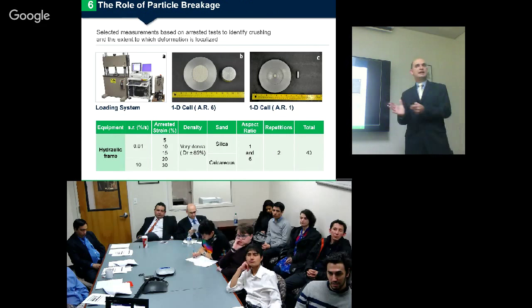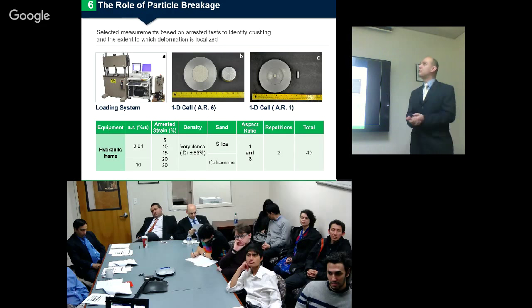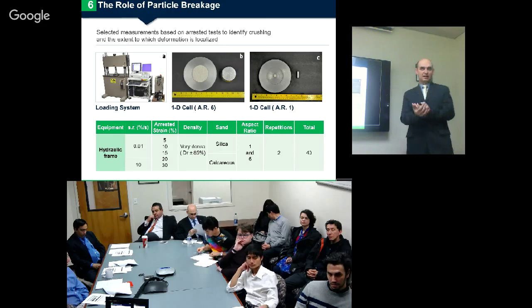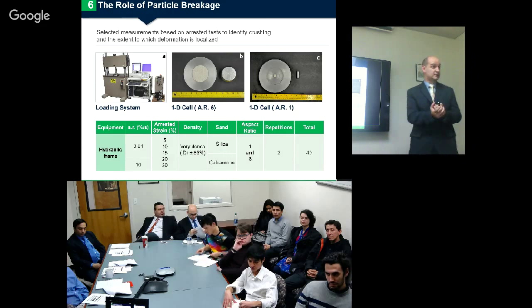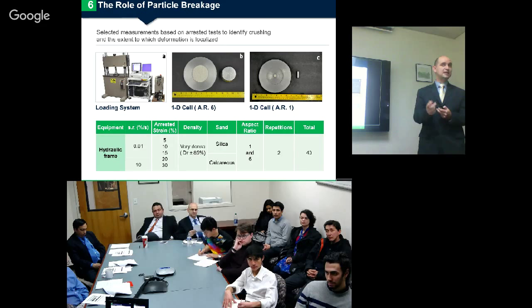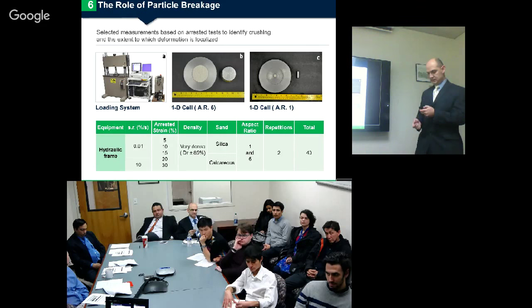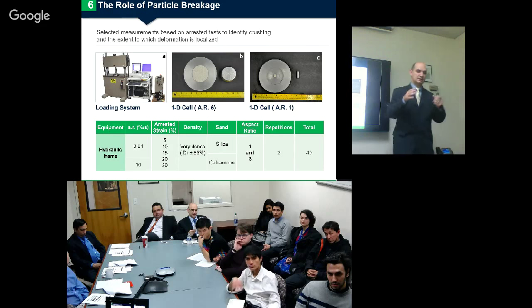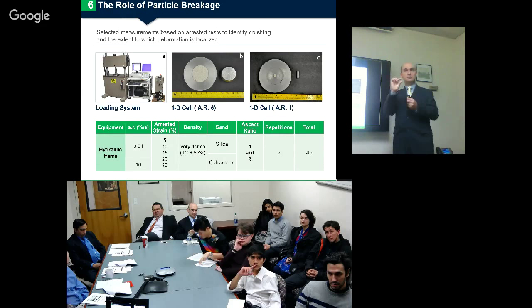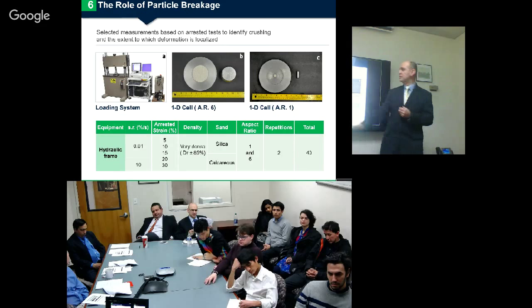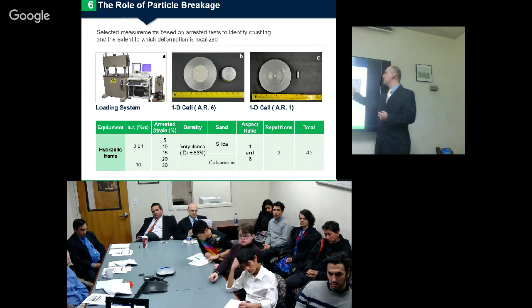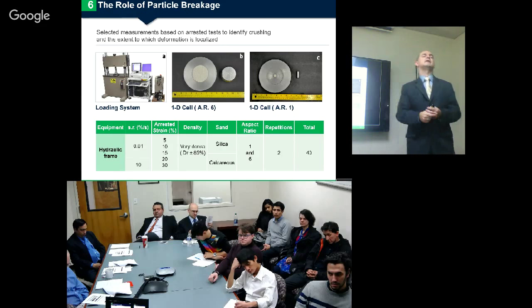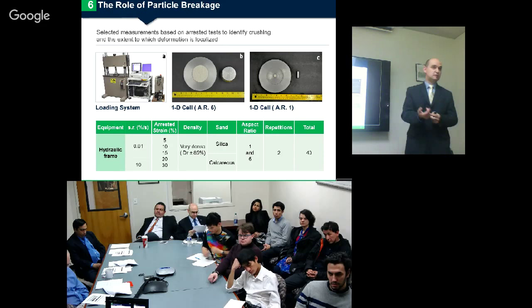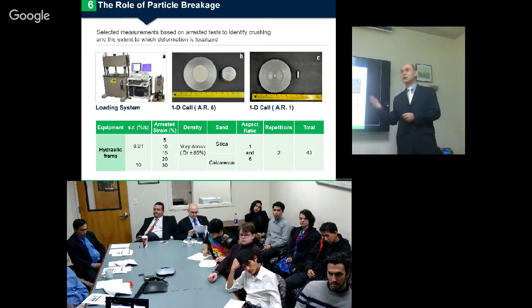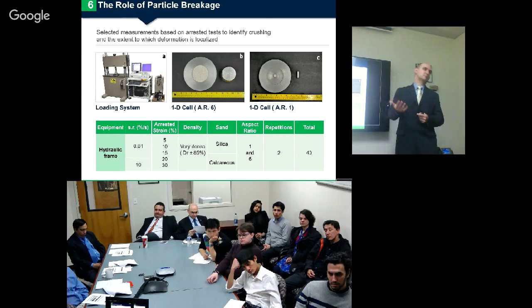Now, after the modeling, I wanted to see also the role of particle breakage by conducting experimental work, again in uniaxial compression tests. 2 different materials, 2 different aspect ratios, or in other words, 2 different geometries. AR stands for aspect ratio. An aspect ratio of 6 means the diameter is 6 times the thickness of the specimen. So for an aspect ratio of 6, I have the same mold. For an aspect ratio of 1, we added a piece in order to make the diameter and thickness dimensions the same. 2 different strain rates in this case: one of the slowest we could get by using the hydraulic frame, and 10% per second is the maximum.